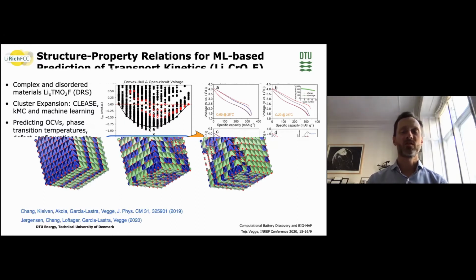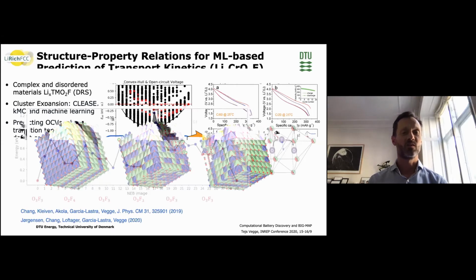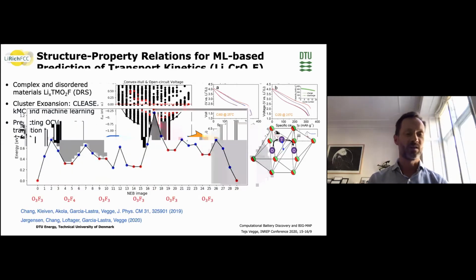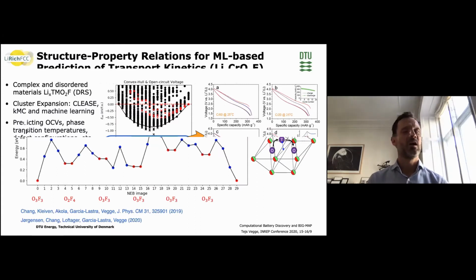And one of the things that we're trying to establish is trying to understand how can we relate structure and transport kinetics. And this is some work where we were combining the method I just described with machine learning techniques, trying to understand how the local structure surrounding lithium when it moves through the lattice or disordered lattice relates to the transport barriers. And what we see here, the blue points that you see here, they represent kinetic barriers.